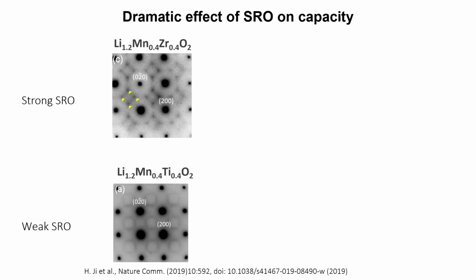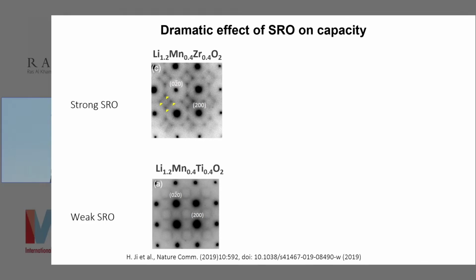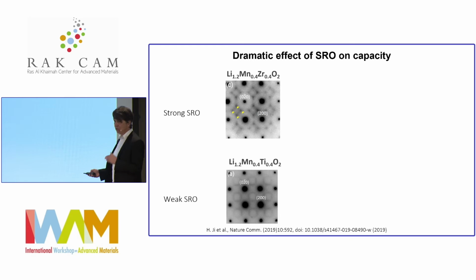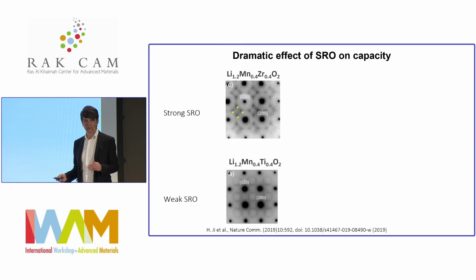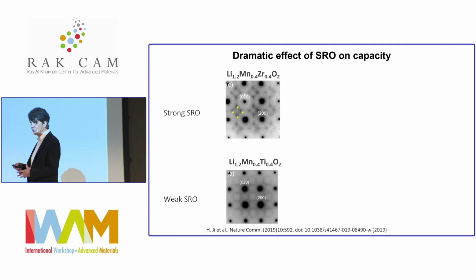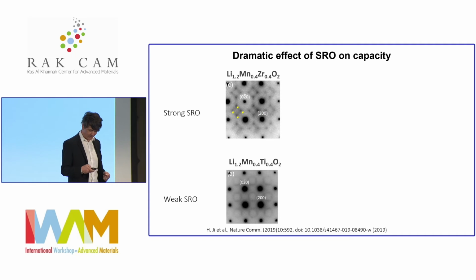So here's an example that didn't turn out the way we planned. And if I can give my message to young people, an experiment doesn't always come out the way you want it, and sometimes it's completely the wrong way, and usually that's a great learning moment where you can actually learn something. So we made two oxides that we thought would be similar, but we thought this one would be better. This is a 20% lithium excess with manganese, and then there's zirconium as an inactive element, and then we replaced that here by titanium. We thought this would be the better material because zirconium is bigger. And we thought zirconium is bigger, so you have better diffusion of the lithium.